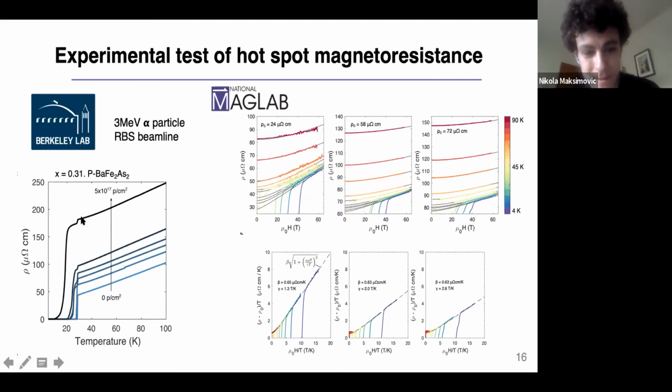It's because the curvature of these curves is changing slightly. It's actually not perfectly T-linear. Especially in disordered samples, you start to see at high temperature that it has this spoon shape. I can't explain why in particular you start to see deviations at high temperature in the context of this model, but it's a reflection of the fact that the temperature-dependent resistivity is changing slightly. Okay. Thank you.